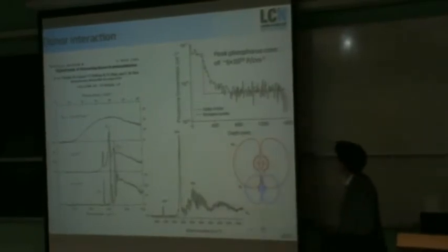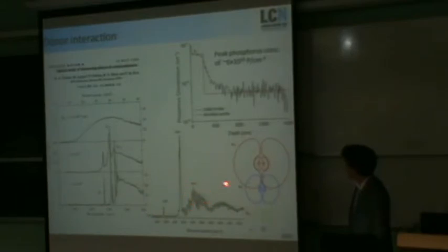So the next question is, why in this typical spectrum don't we see the higher lying excited states? And this again is answered by a plot Gabriel showed yesterday. Basically, if you have a high concentration of phosphorus present, you start to get an overlap of the higher lying excited states, and so they're no longer sharp, and you get a smoothing over. What you do see here is a lot of fringes. This is just a Fabry-Perot interference between the top and the bottom of the sample, and you shouldn't be confused with actual peaks.